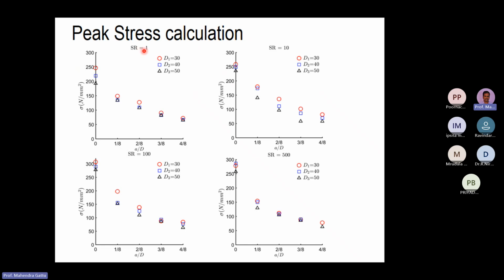And this is the experimental data which we get for each loading rate. So here we have 1 millimeter loading rate, 10 millimeter, 100 millimeter, and 500 millimeter. What we're plotting is the peak stress values on the y-axis, and the a by D ratio on the x-axis. So a by D means the notch depth by the diameter, the size.